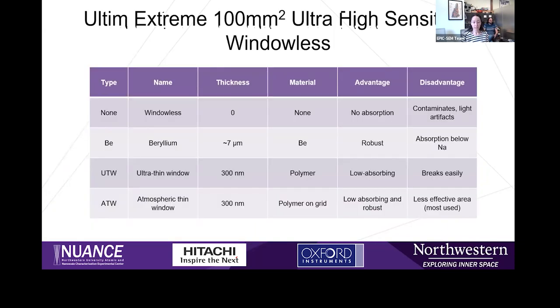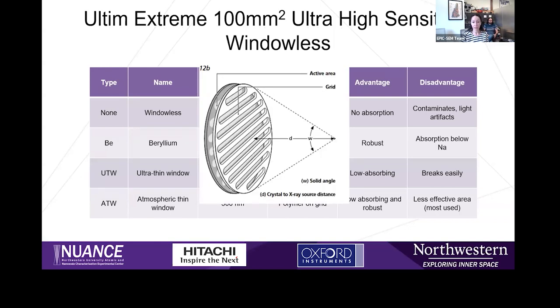So why is this detector so good for that? The most notable feature about this detector is that it's windowless. If you're not sure what that means, EDS detectors often have a protective barrier or film on them that helps protect the detector crystal from contamination and also helps to maintain the vacuum inside. The problem is these windows can absorb low energy X-rays before they hit the detector. All our other EDS detectors at Nuance have windows, so this EDS detector will be unique here for that.